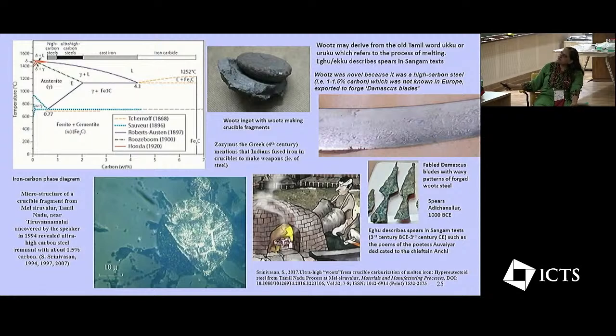And this is typically the microstructure that you see. And basically, austenite here has this kind of hexagonal structure. So it's the prior austenite structure from which, when it has come down from slow cooling, you see here the cementite needles and the pearlite within the cementite. And this pearlite surrounded by light cementite is what, when it's forged, gives this typical composition of wootz steel. And here you also see, of course, some very fine spears from Adichanallur.